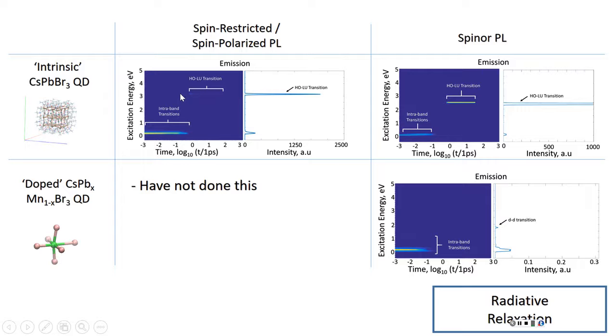But basically it relaxes here for 100 picoseconds, first radiative lifetime, and then we can see the peak here, which is just summing up each emission. And the intensity comes out about 10 to the third units. But when you compare that to the spin-polarized case, the intraband transitions aren't as bright, and the brightest one is the HOMO-LUMO. It's not shown on here, but the intensity of this one is up to 10 to the fourth, so it's about 4 times more intense, which kind of corresponds to our spectra because the HOMO-LUMO peak is about 4 times higher, so we get 4 times more intense PL.